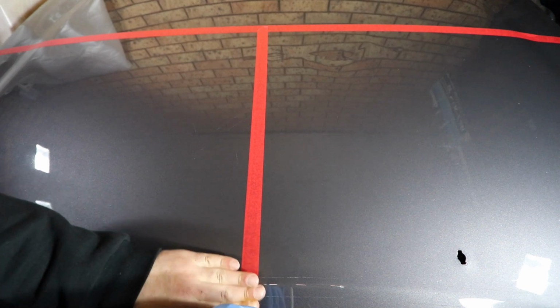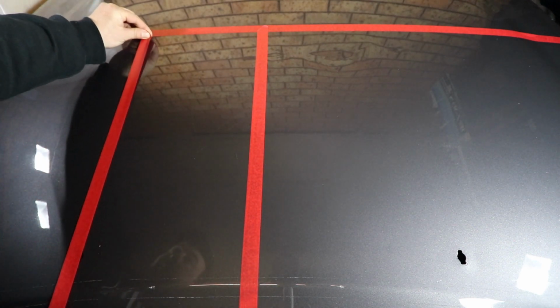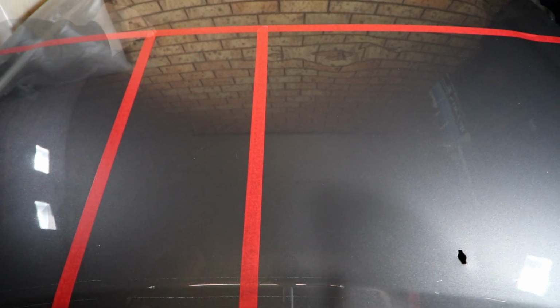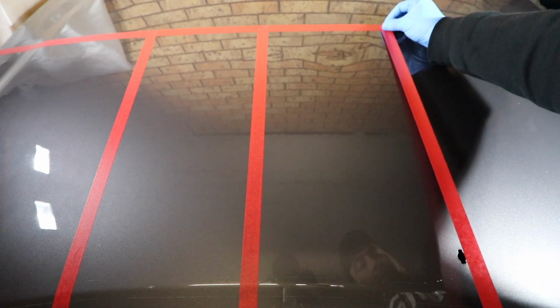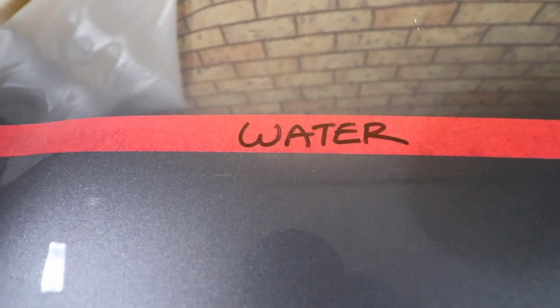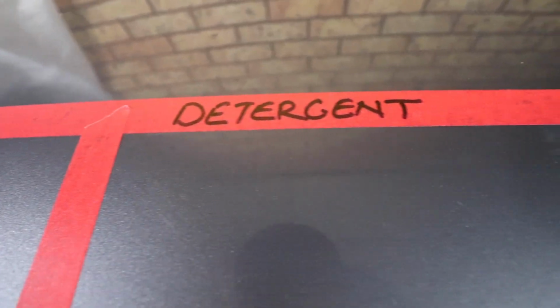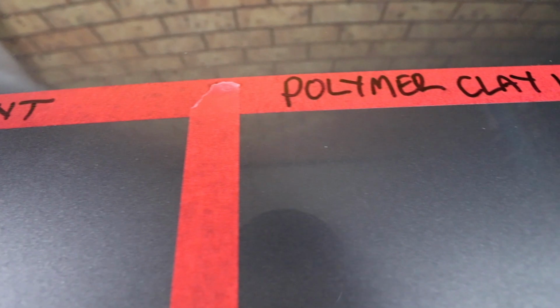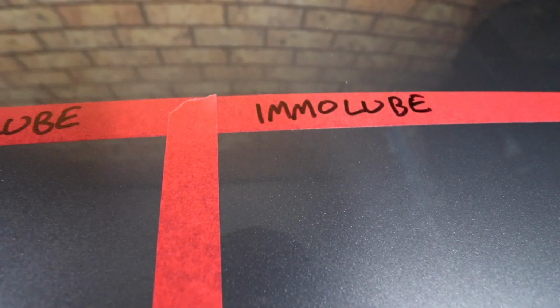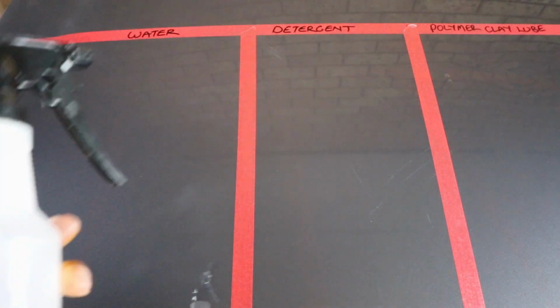After the vehicle has been deep cleaned with detergents and stripped with chemicals, all of which are primarily used to get the paint as bare as possible prior to polishing, it's really not the best idea to then go and use a product with strong bonding polymers, as most clay lubricants contain, as these polymers, in my experience, will not simply wash or rinse off, or even be completely removed with a final IPA wipe down, and ultimately they will be present when you begin polishing the paint. And as I stated before, they will slow and negatively alter your paint